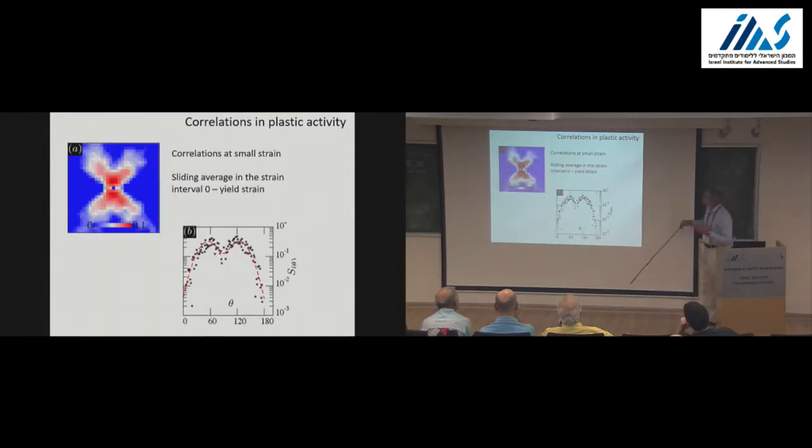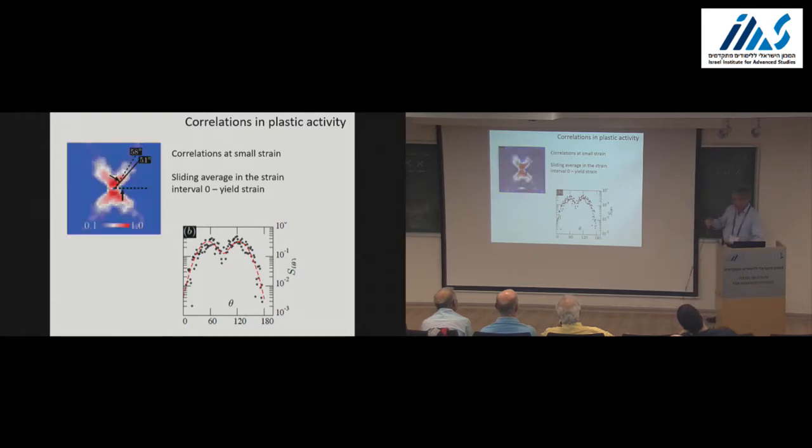For the part that is before yield stress, the data is much more difficult to collect because you have relatively few events and little statistics. But essentially, we get that the data is more blurred. There are more possible orientations. If we look at what it gives, we get an angle here, but I wouldn't necessarily insist on that. It is in between 51 and 58, so presumably it's some kind of mixture of the shear bands and the isolated events.